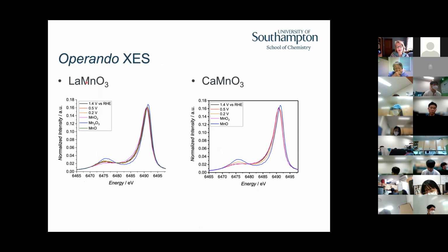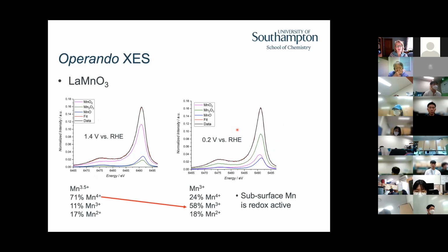So here is our lanthanum manganate and our calcium manganate as a function of potential. And you can indeed see that we're seeing the shifts in these peaks, right? And we've got more information here, is the important part. When you did the oxidation state from the edge position, you only had one parameter, so you can only fit one parameter. But I want to fit the population, not just the average oxidation state. And so by doing this and fitting the data to our references, we can then fit the spectrum as the components. And what we can see is that for the lanthanum manganate, the average oxidation state was 3.5, and it was made up of 71% manganese 4, 11% manganese 3, and 17% manganese 2.